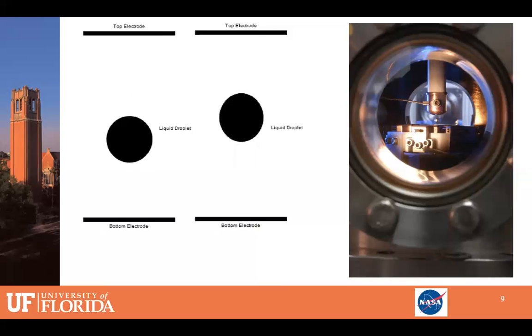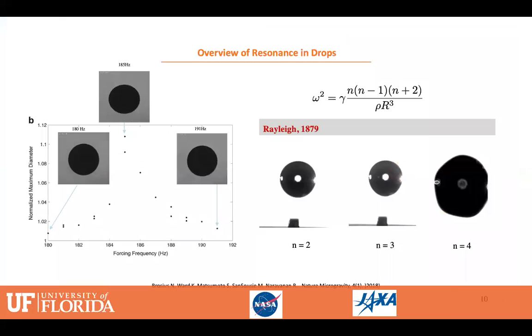And that natural frequency correlates directly to the surface tension. So what we have here, on the left, is an actual image taken from experiments done at NASA Marshall Space Flight Center of a zirconium droplet at 1800 degrees C. And you can see that at about 185, this droplet goes into these excited modes, whereas at less than 185, the excursion is very small, and at greater than 185, as shown to the right, let's say about 191, the excursion is also very small. So there's really this optimum frequency at which the excursions are very large.